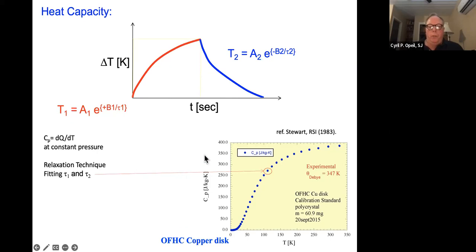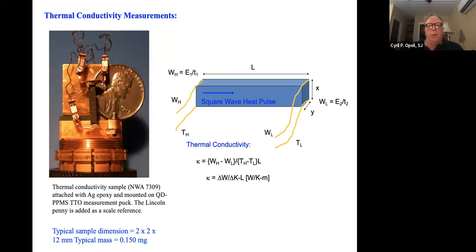I actually have some sample data here. It's an OFHC copper disc, and this copper disc has been measured. These numbers here, tau 2 and tau 1, are the parameters by which you derive the specific heat capacity of a particular material at a particular temperature. Enough said. The second technique has to do with thermal conductivity measurements.